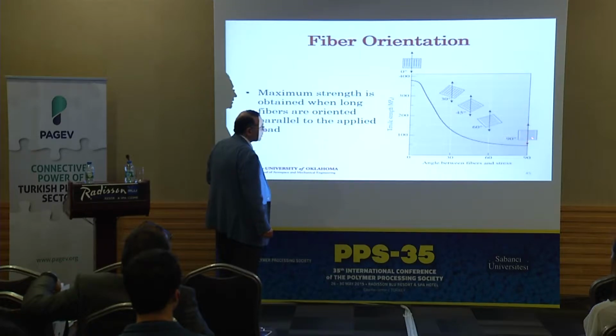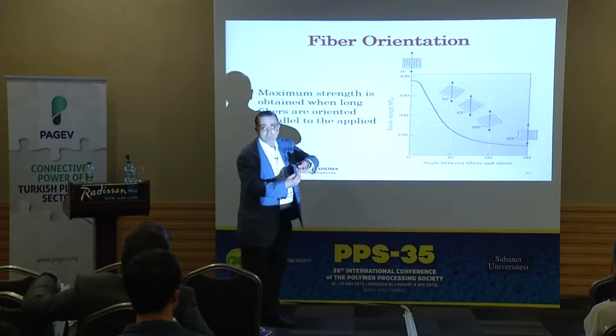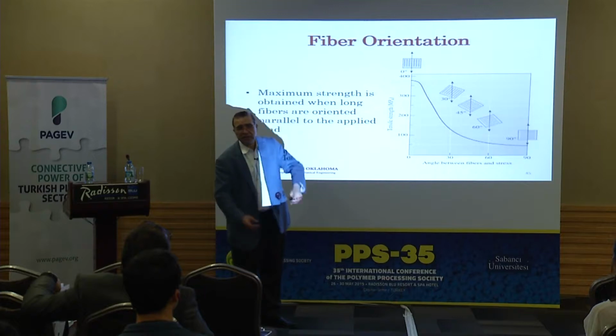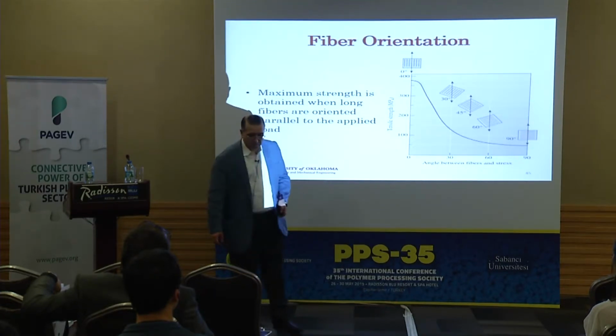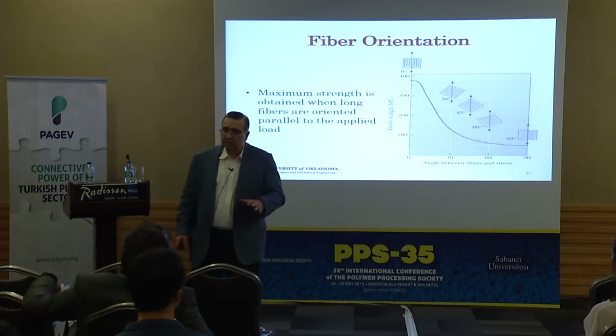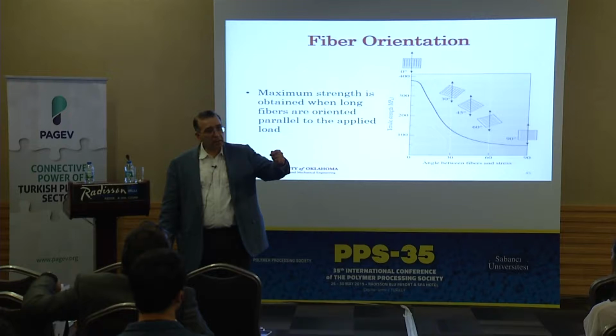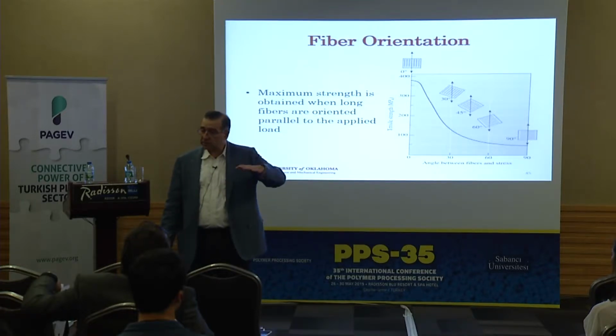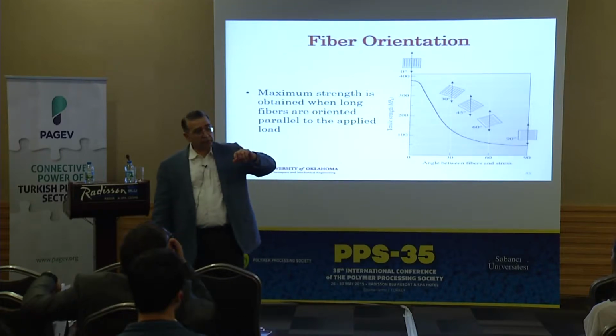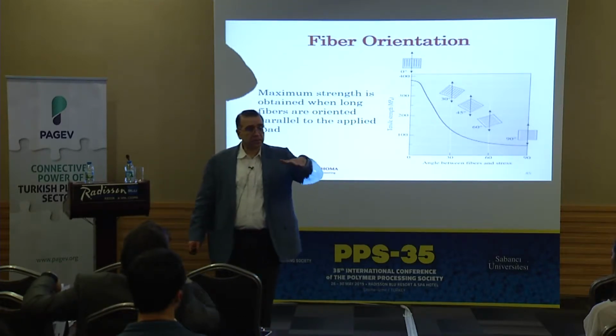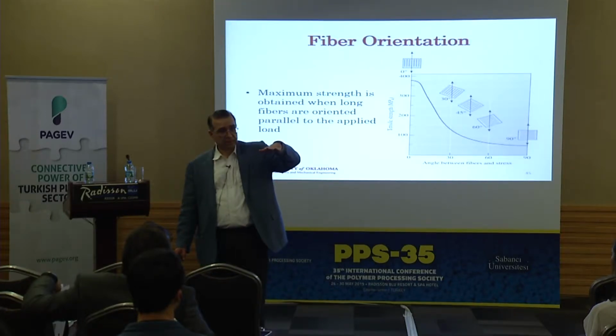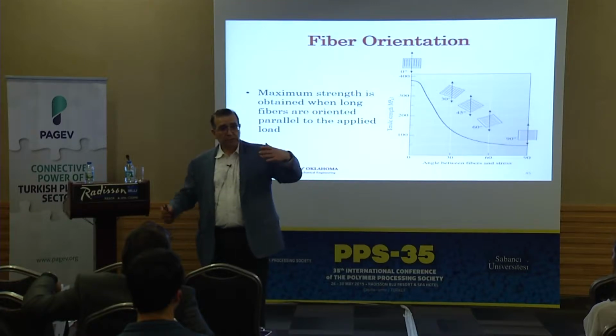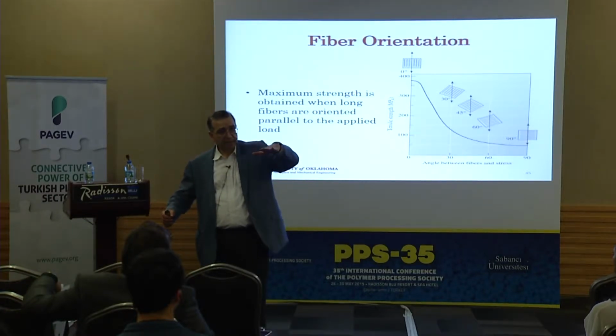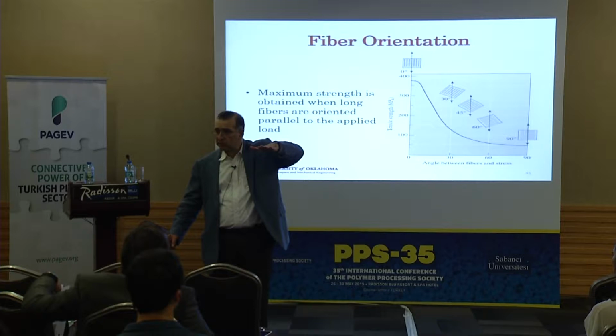So most people account for these off-alignments in their design. In the transverse direction, the properties are very poor because when you apply a tensile stress, you are essentially pulling apart the resin. The fibers will not really help you a whole lot when you have that. So in making laminates, going back to F16 structure, wing structure, F16s, the first prepregs with the carbon fiber, they were unidirectional prepregs. So the fibers are all in the same direction. To make the part, you have to stack up these layers in such a way that you rotate the fiber orientation layer by layer, right?